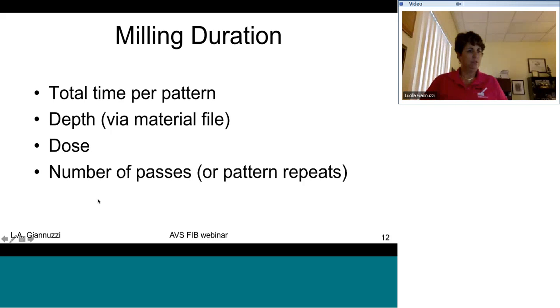Okay? The milling duration can be defined by the total time per pattern, the depth via some material file that may be built into your system, or you can define the dose, or you can define the number of passes or repeats. Of course, if you change any one of these things, all the others will change, because these are all tied to each other. So if I define a depth via a material file to be, say, 5 microns, this will automatically define the total time per pattern. We'll already define a dose based on the size of the pattern, and we'll then define the number of passes based on the dwell time. If I change any one of these, the other things will change because they are all tied to each other.